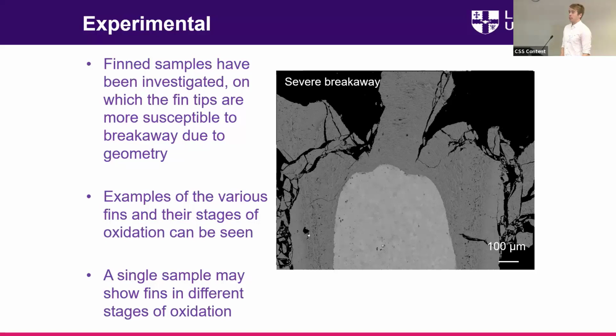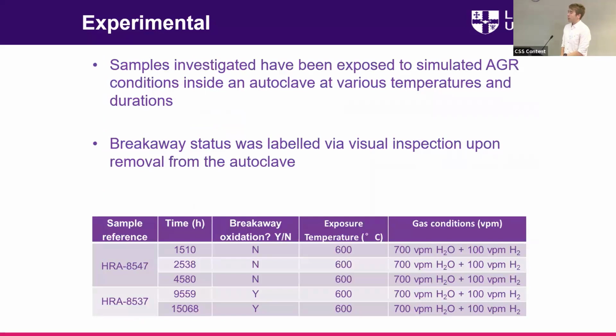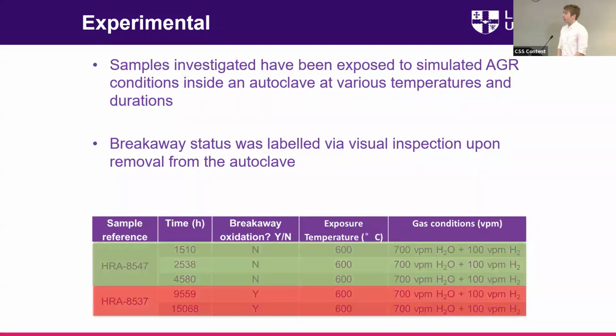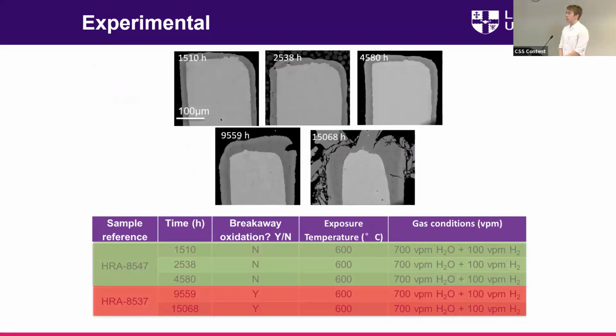And a single one of these fin samples may, depending on which fin you're looking at, actually show different stages of breakaway oxidation. So the samples that I'm going to be talking about have been exposed to simulated advanced gas cooled reactor conditions inside autoclaves, and the breakaway status of the sample was labelled upon removal from the autoclave. So we range from about 1,500 hours to, I think it's about 15,000 hours, and they've all been exposed at 600 degrees C. So here's just a quick visual comparison of the fins as they increase in exposure time.